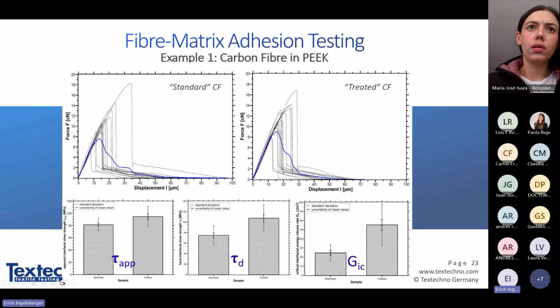This here is a comparison between a standard and a surface treated carbon fiber embedded in PEEK. This is the standard fiber, and this is the surface treated fiber. This is the apparent interfacial shear strength, measured by the maximum force. This is where the crack is initiated, the local interfacial shear strength. And this is the energy release rate. You can see very clear differences between a standard and a surface treated carbon fiber.